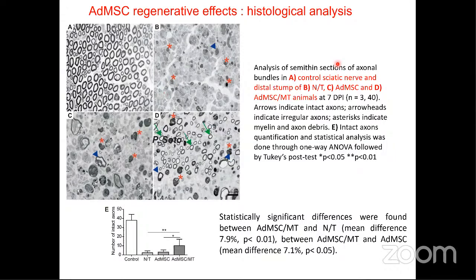So I was saying that Paula has analyzed the regenerative effect of adipose derived mesenchymal stem cells through histological analysis after 7 days of treatment. You have here a control, where you see many myelinated axons, very nice. You have here what is degenerated and not treated. You don't see the myelinated axons. Here you see a mouse that was treated just with cells. You see some recovery, very low recovery, and now this is the one treated with cells loaded with magnetic nanoparticles and treated with the magnet. And you see there are many axons that are recovering.